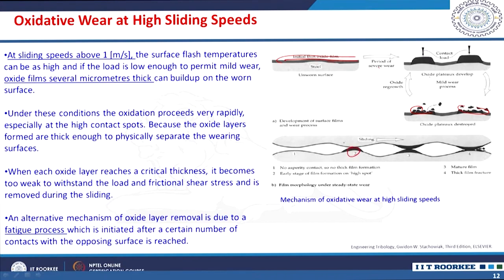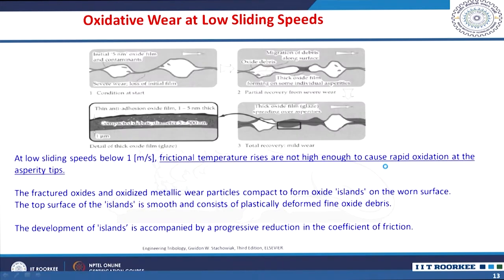So you can see no asperity contacts first of all, and then asperity contacts leading to high hot spots, and then this material is removed. So, with increasing speeds you have a difference in the oxidative wear, right? An alternative mechanism can also be understood as the material is removed due to a high fatigue process, which is initiated after a certain number of contacts with the opposing surface is reached.